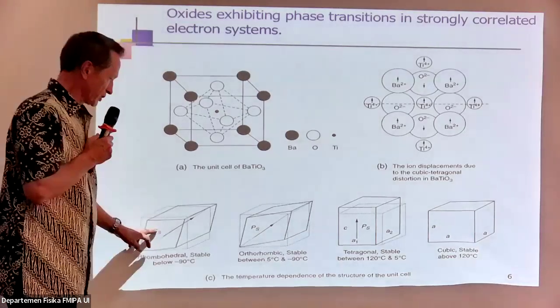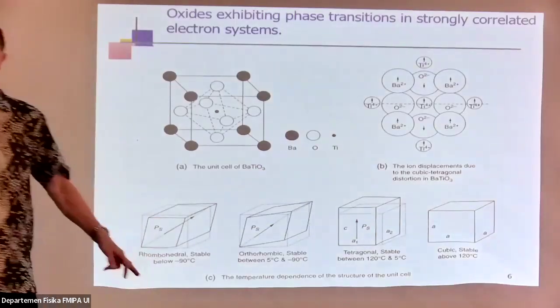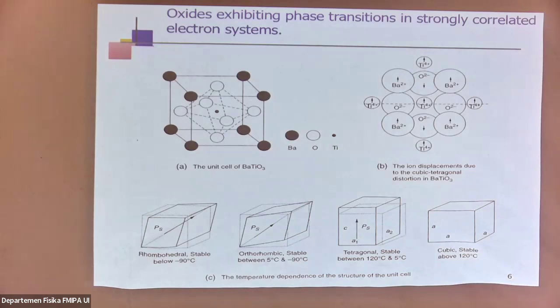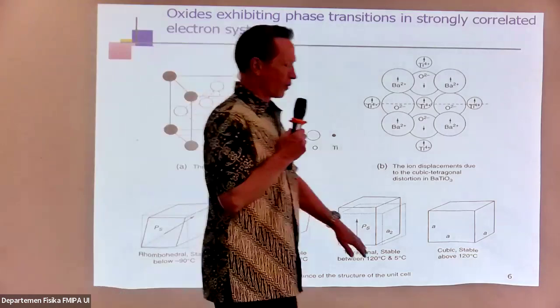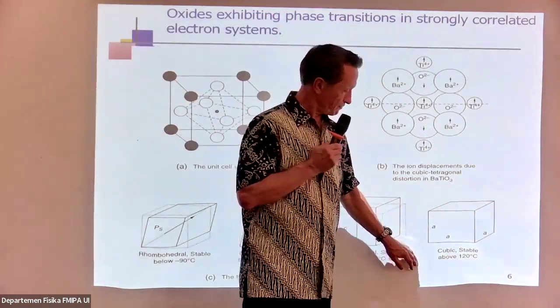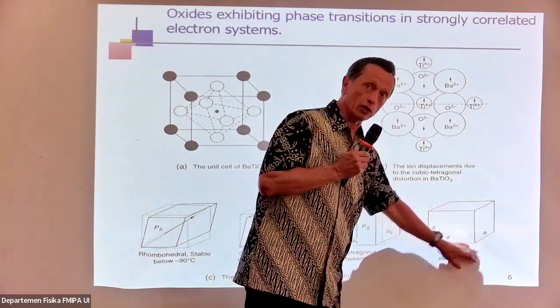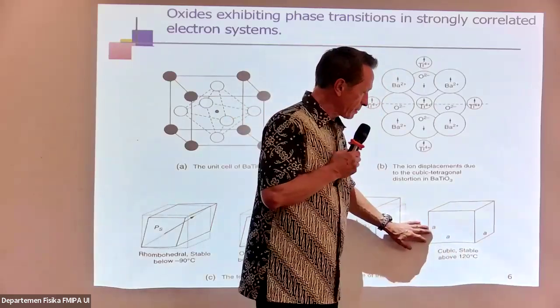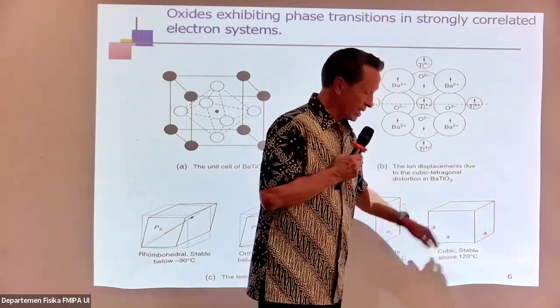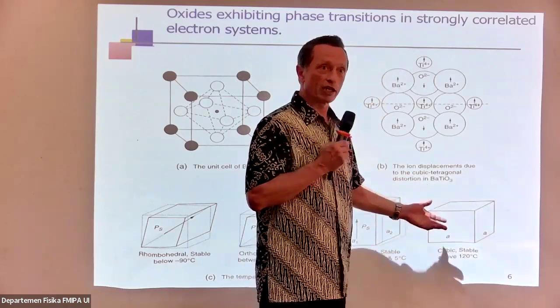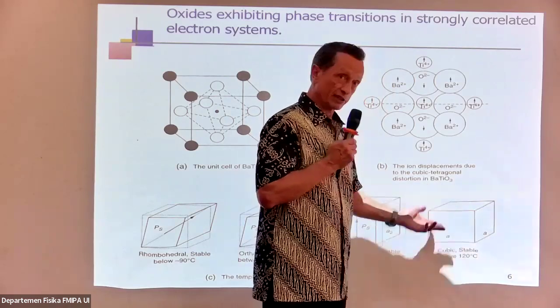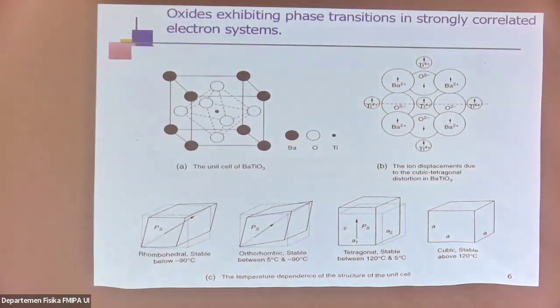That means you will have an internal polarization with different direction as a function of the phase, and this polarization will define all electrical properties. And when you go above the famous Curie temperature, so for barium titanate, it's something around 120 Celsius degrees, the material becomes a cubic material. That means in the cubic phase, this cube is really a perfect cube. That means all dimensions are similar, are equal. And of course, here it's an example for barium titanate. But if I dope this material, I will modify the different temperatures related to the different phases. For another material, I will have, of course, different phase transitions.